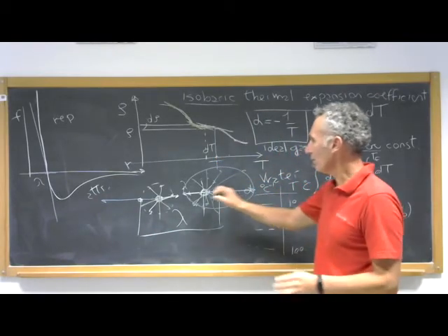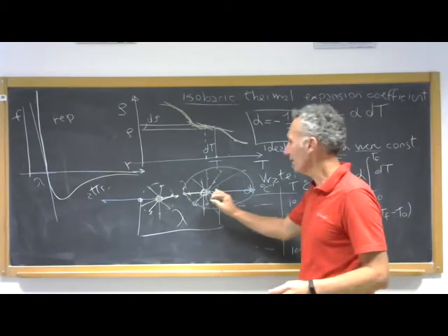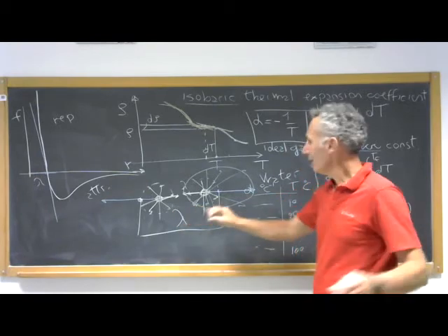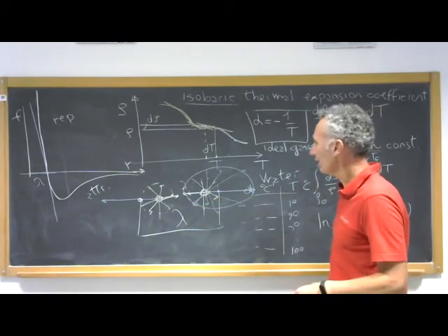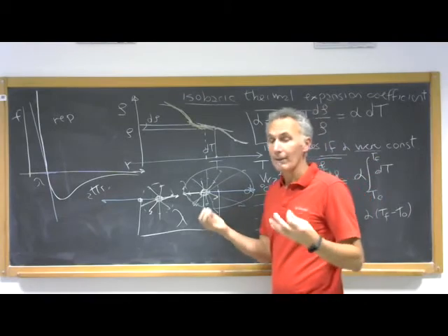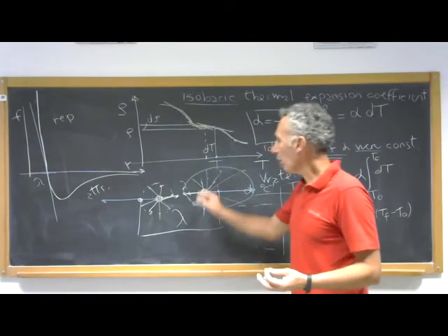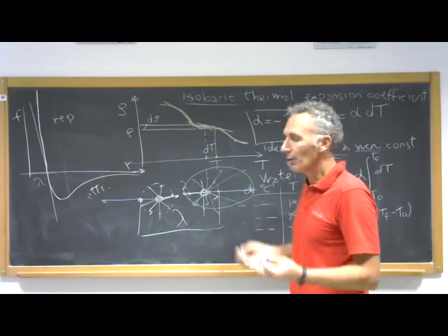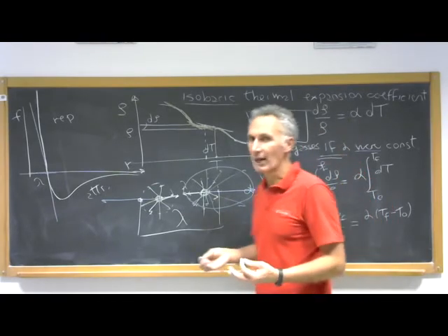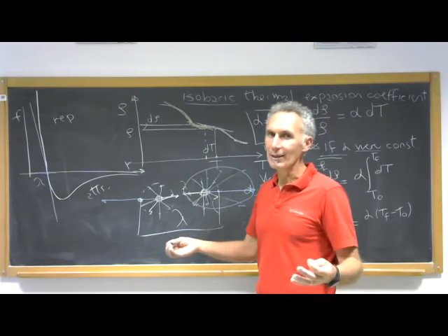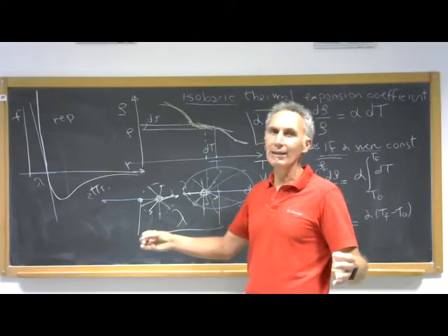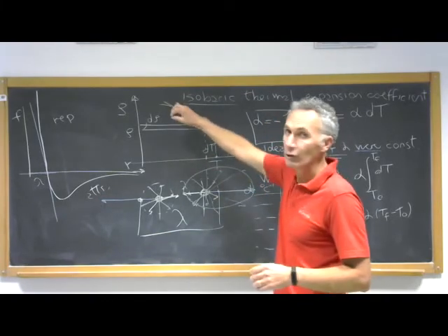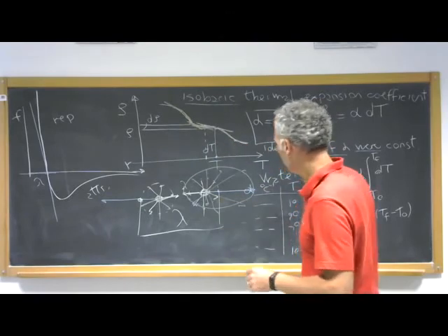Because in these fluctuations, the variation is not symmetric. When they get closer, they get less than they should, and when they get far, they get more than they should. And so, overall, the same number of molecules, of units, is increasing the average distance. So the same number of units implies the same mass. Increasing their average distance implies increasing the volume occupied. And so this explains why, for increasing temperature, the density decreases.